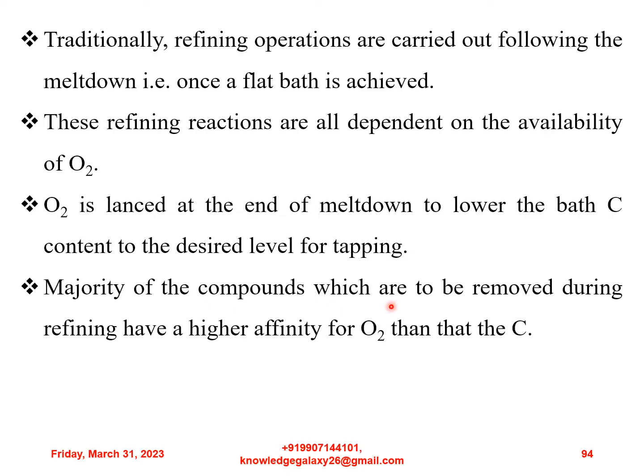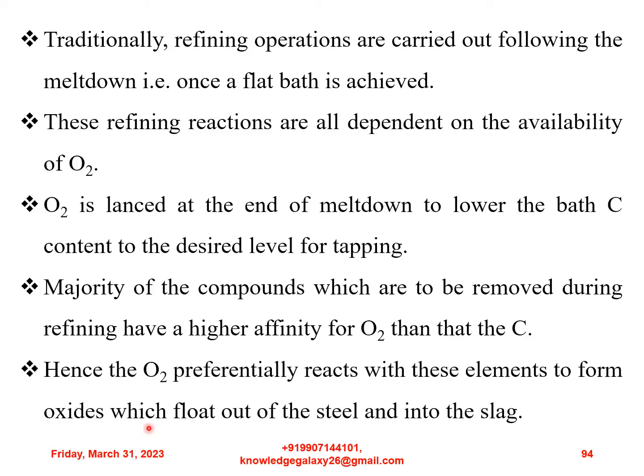Majority of the compounds which are to be removed during refining have a higher affinity for oxygen than for carbon. Hence, the oxygen preferentially reacts with these elements to form oxides which float out of the steel and into the slag.